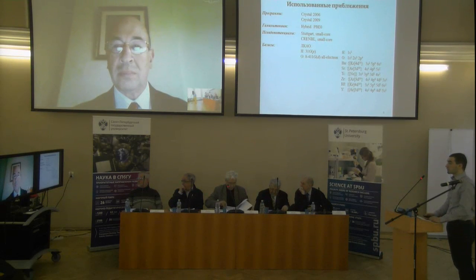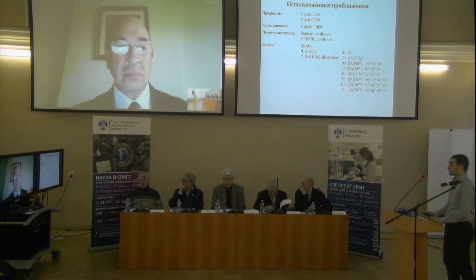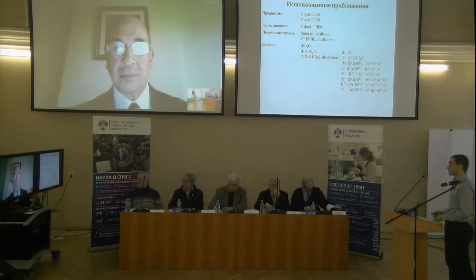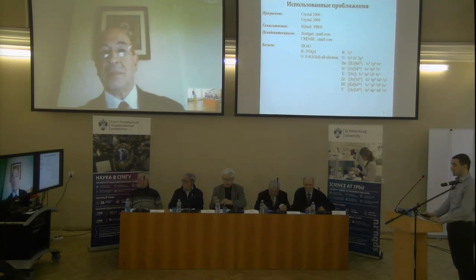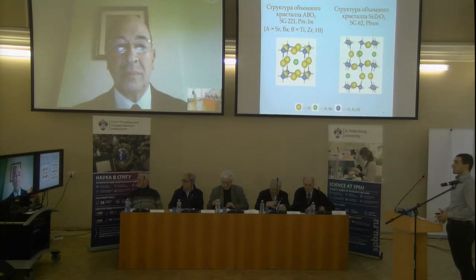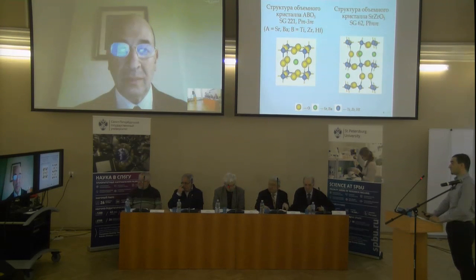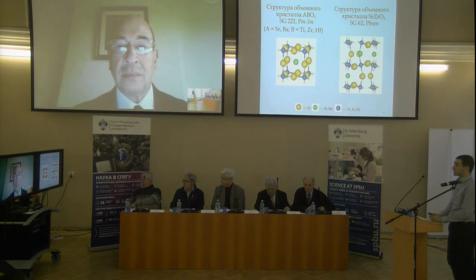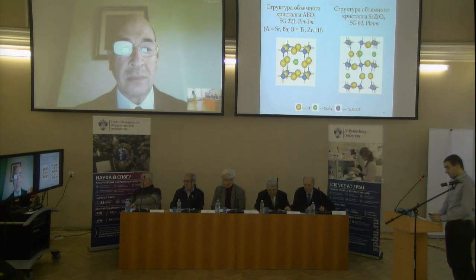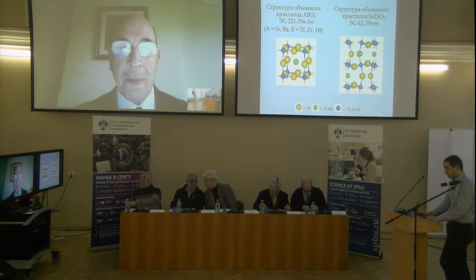The computer program Crystal was used to perform the calculations. Quantum chemical calculations were performed by the DFT method using the Hybrid exchange correlation functional. The functional is successfully used in calculations of the bulk and surface properties of perovskites, and also reproduces the parameters of hydrogen bonds with the participation of water molecules. To describe the interaction of the core and valence electrons of barium, zirconium, etc. atoms, pseudo-potentials with small cores were used. For atoms of oxygen and hydrogen, a full electron basis was used.